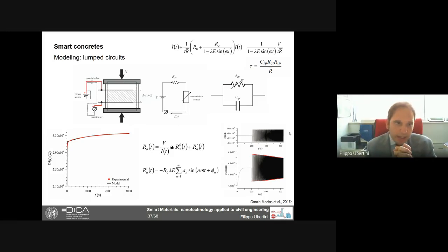And this model is very nice because it can reproduce the polarization pretty well, as you see in the bottom left. It can reproduce the presence of superharmonics in the response to a sinusoidal mechanical load, which can be seen by analytic derivation through manipulating the differential equation that governs the circuit. That is a linear differential equation, but has time-varying coefficients. But what we could not reproduce was the increasing frequency response function with increasing frequency.